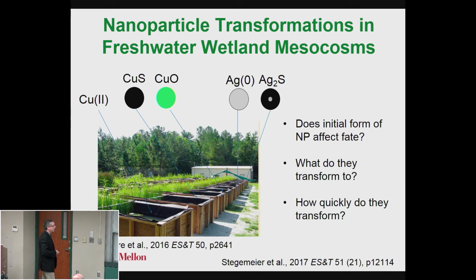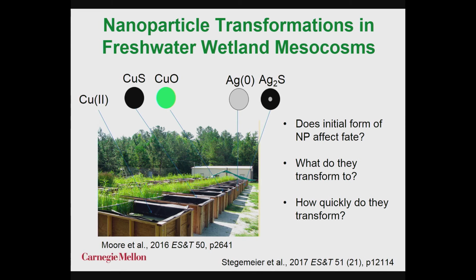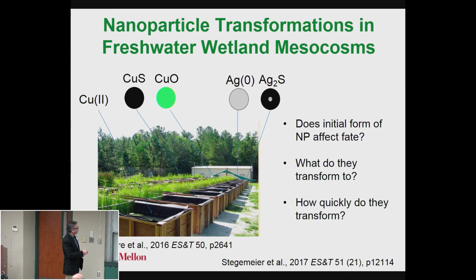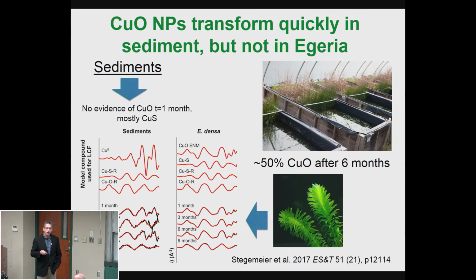All right, so we also looked at these nanoparticle transformations in wetlands. We wanted to know how fast they occurred. We wanted to know if they occurred. And we did things like put copper oxide and copper sulfide into a mesocosm, or silver zero and silver sulfide. And we wanted to know, does the initial form entering have any impact? If I put a reactive material in, what does it transform into? And how quickly does that happen? We wanted the kinetics of this particular system. And we were a little bit surprised by some of this.